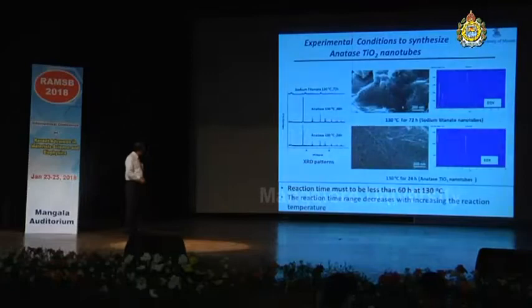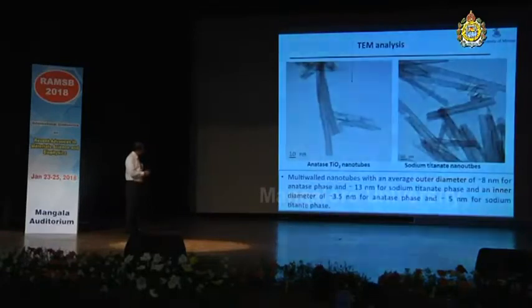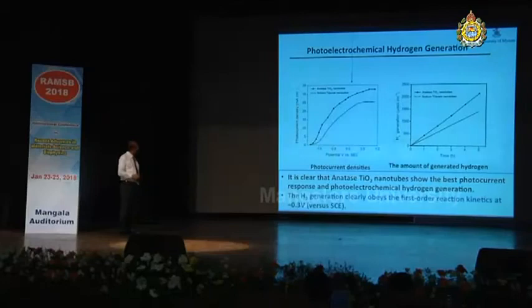The reaction time decreases with increasing the reaction temperature. That also we have studied in detail. And this is the ideal condition, about 60 hours duration and temperature about 130 degrees C. And these are some of the TEM images of the nanotubes of titania we have synthesized. The multi-wall nanotubes with an average outer diameter of about 8 nanometers for anatase phase, and about 13 nanometers for the sodium titanate phase, with an inner diameter of about 3.5 nanometers for anatase phase and nearly 5 nanometers for the sodium titanate phase. We are further working on these to come out with the control to optimize the conditions.